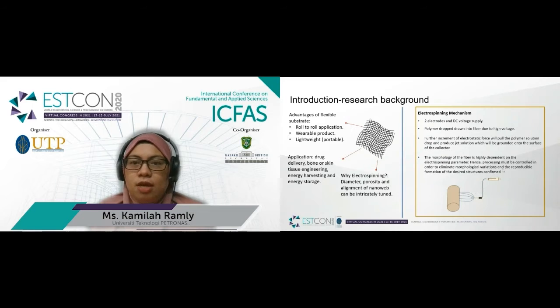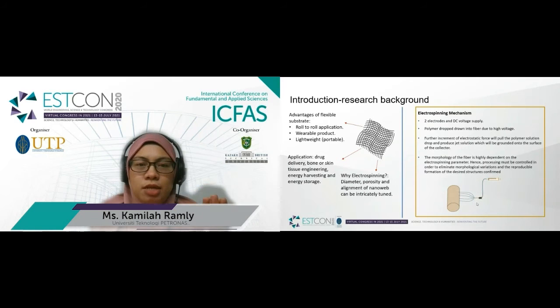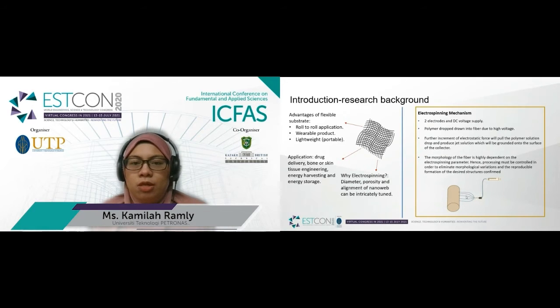Typically, an electrospinning setup consists of two electrodes. One is the needle and the other is the collector. Initially, the drop of polymer solution injected by the syringe at the tip of the needle is spherical in shape due to its surface tension. When voltage is applied, electrostatic force will overcome the surface tension, transforming the spherical shape into an oval shape and finally deforming into a conical shape called the Taylor cone.